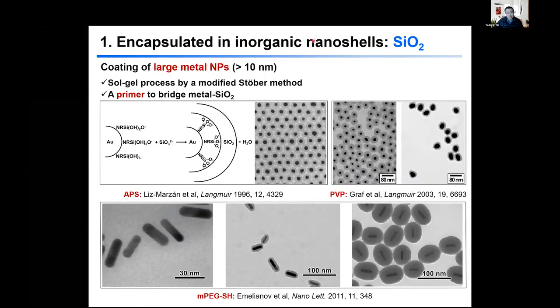The first type is to use inorganic nanoshells. And typically we use silica. Silica is well known for its sol-gel chemistry, very easy to do, and a room temperature reaction. The reaction is basically hydrolysis of organosilane, and we produce silicate. The silicate is deposited on the metal surface, and then we form a coating and encapsulate particles inside. The challenge here is that gold, for example, and silicate don't really like each other, so we actually need a primer or linker or a coupling agent to connect the metal surface and the silica. People use different types of linkers or primers, for example, aminosilane, the polymer PVP, or thiolated PEG. And once you have those, the coating becomes very easy.